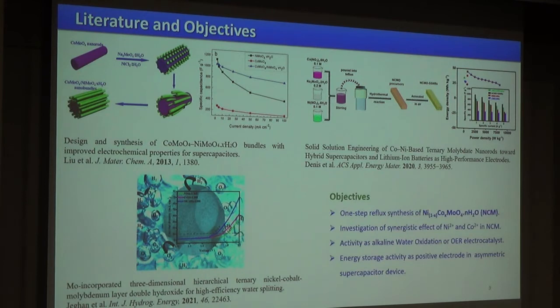So these are our objectives: one step reflux synthesis of this material, and further investigation of the synergistic effect of nickel and cobalt and their energy conversion application as a water oxidation or oxygen evolution reaction electrocatalyst, and its energy storage activity as a positive electrode material in an asymmetric supercapacitor device. Most of these earlier studies involve two-step or multi-step synthesis reactions, and they have studied either energy storage activity or energy conversion activity only.